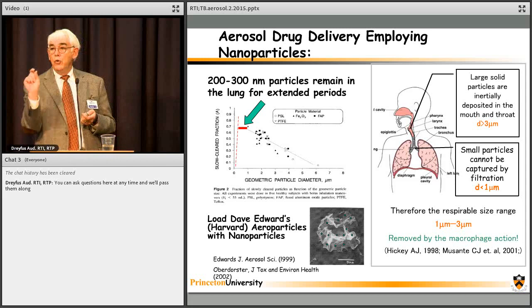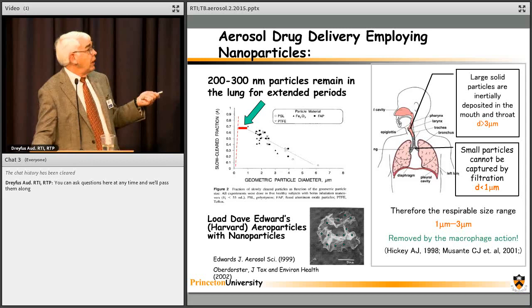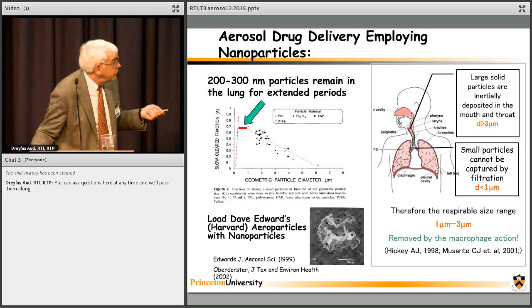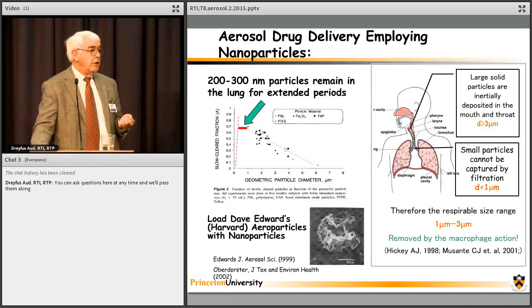period of time. But if you have drugs in this size, it's extremely difficult to aerosolize or inhale or capture them in the lungs. So this is actually Tony Hickey's reference right there, showing that you want particles in this 1 to 3 micron range. Too small, they breathe in and out, they're not captured. Too big, they impact the back of the throat and aren't captured. So how do you do these two things?